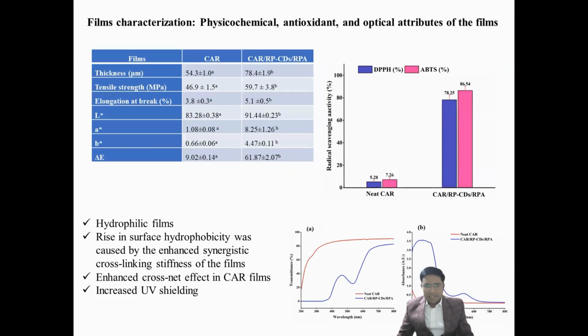Coming to the next, the film characteristics. The thickness, the tensile strength, the elongation at break, these are the different parameters. We found that the physical and chemical properties are improved. The films formed are hydrophilic films, but there is an increase in hydrophobicity. We found good cross-linking and enhanced cross-linking effects in these carrageenan films, and increased UV shielding. UV shielding has been found to be increased. The reason might be that carbon dots are very good UV blockers. So these were the findings for that.